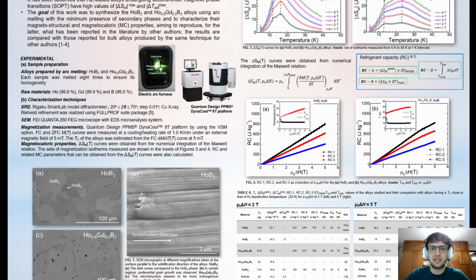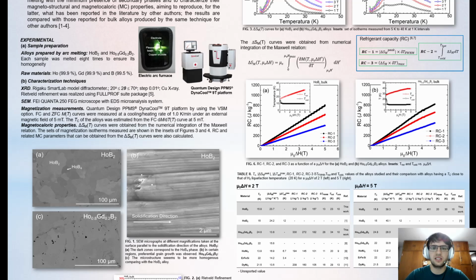The refrigeration capacity of these alloys was also calculated under certain criteria reported in the literature that we can see in these equations. As seen, the values obtained are quite high, and we can see them in the figures 6. The inset graphs show how the temperatures of the hot and cold receivers vary with respect to the magnetic field variation. And well, these hot and cold receivers represent the working range of the temperature, the working range of the alloys.